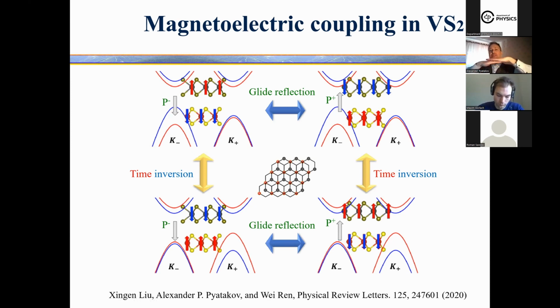In fact, its spontaneous state corresponds to some shift of the two layers with respect to each other. And when there is a mirror reflection and translation transformation, the electric polarization can be switched with an electric field.